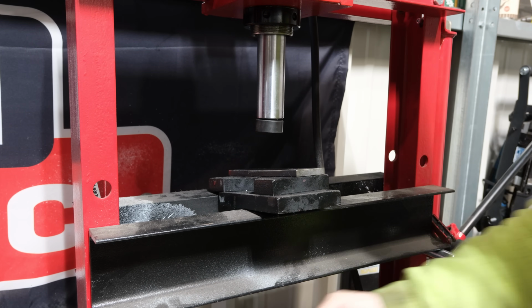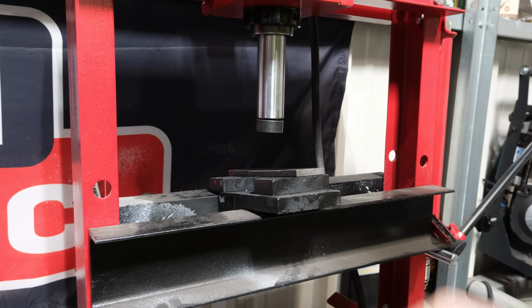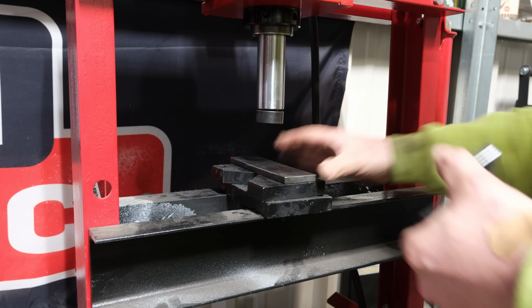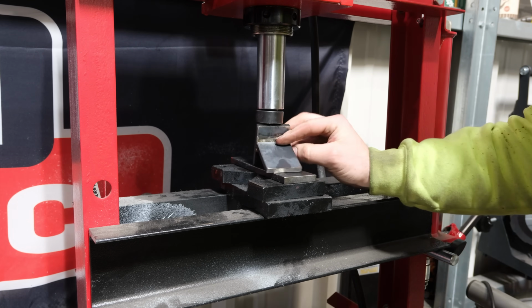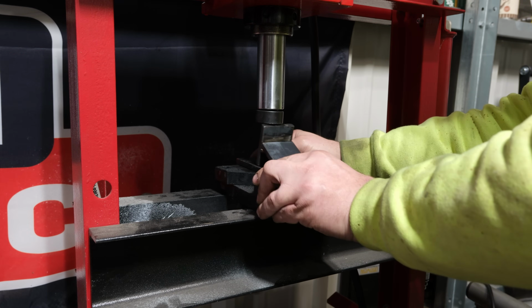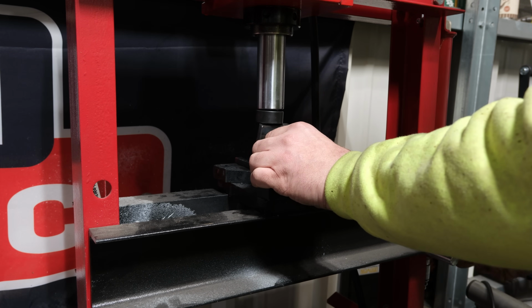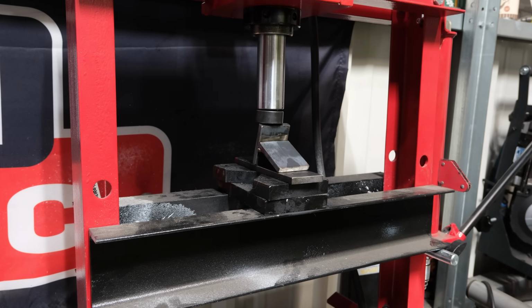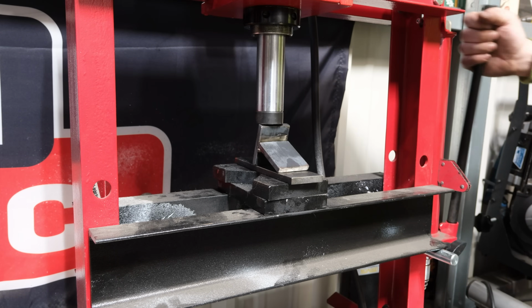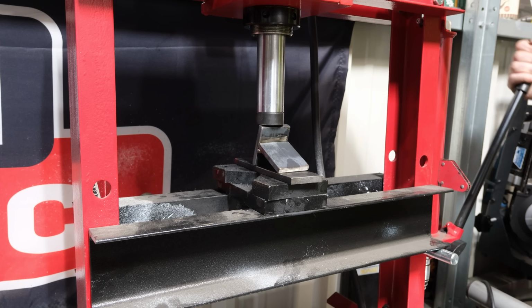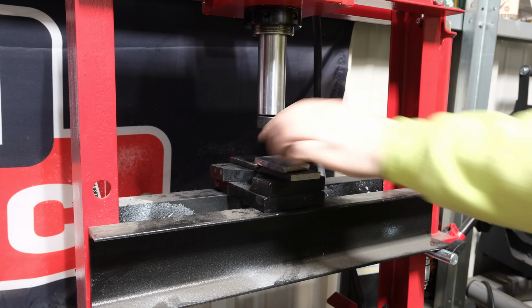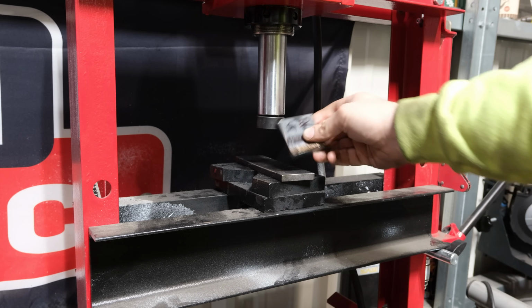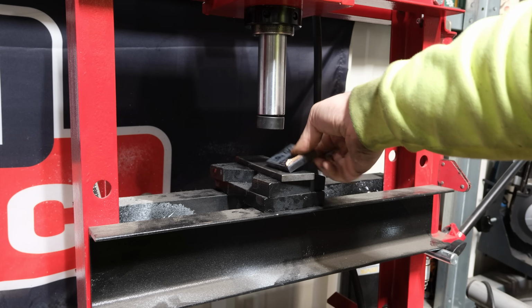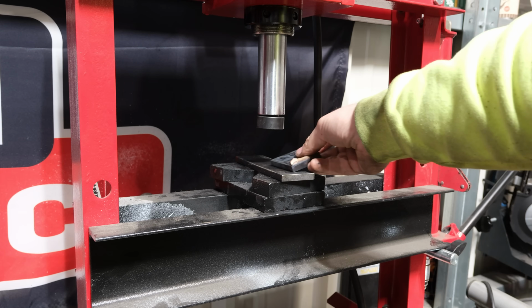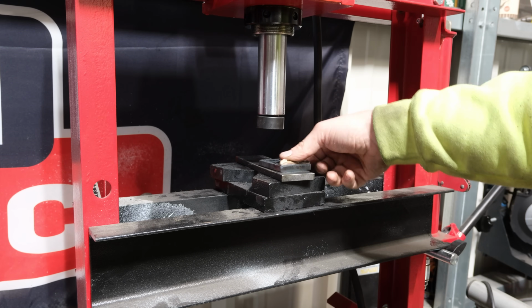And not too surprising, looks like the braze failed. Up next is a multi-pass, and considering how brittle that normal silicon bronze was, I don't have too high of expectations that this is somehow going to hold on. Yeah, I'm going to take a guess and say that was probably cracked and fairly brittle. So multiple pass with that, fast and hot, probably pretty limited.